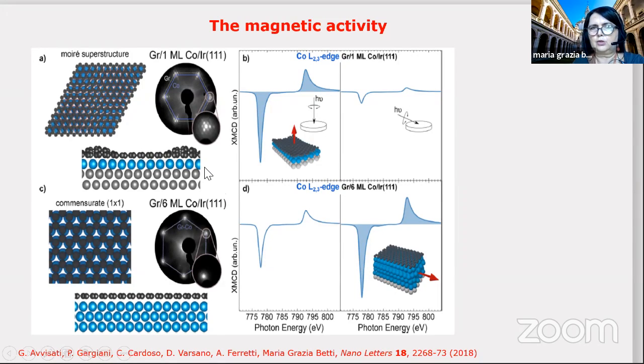Then we go on, and we try to understand how it changes if we intercalate more cobalt layers. So the system we started with is a single layer of cobalt intercalated under the rippled graphene, and this intercalated cobalt is commensurate with iridium. This is the LEED pattern, and this is the dichroic signal, and this dichroic signal demonstrates the magnetic anisotropy: the easy magnetization axis is perpendicular. Then on the other side, we will have 6 monolayers of cobalt. In this case, the system relaxes, and the cobalt layers are almost commensurate with graphene. So you don't see the moire superstructure.